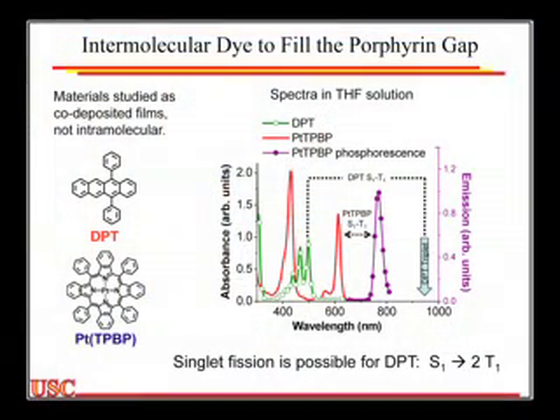And the reason, let me just lay this out here a little bit. Remember that I said that we were screwed and we couldn't do better than about 25%, 30% because of the fact that everything that I absorb relaxes to the energy gap. Right? And so one solution was to make stack cells, which is very expensive and very painful. Well, singlet fission gives us a different approach, right? Because let's say we have the same thing, and I've broken my spectrum here into a green part and a red part, just for simplicity. But no matter where I absorb, I thermalize from the high energy absorbers down to the bottom. And that's a big problem.